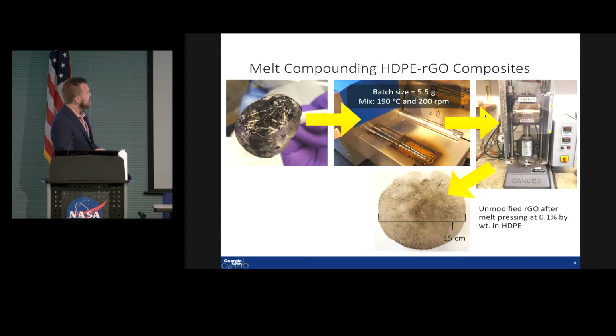In this particular case, this is the regular reduced graphene oxide without our chemical modifications, and we can see there's clear signs of aggregation, and this is after going through all the melt processing that we're going to do with it.